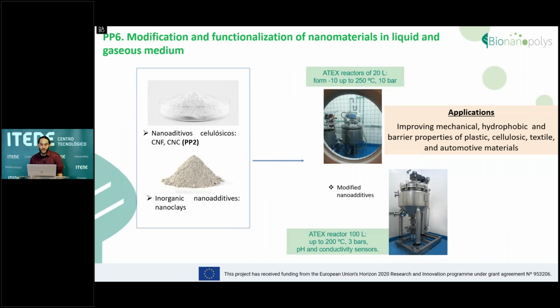Firstly, we can modify both the cellulosic nanoadditives like cellulose nanofibers and nanocrystals and inorganic clays with our ATEX reactors. As I was saying, these ATEX reactors allow us to go from 20 liters to 100 liters and temperatures up to 250 degrees Celsius and apply pressure as well. We have detectors in our ATEX reactor of 100 liters that allow us to follow the reaction using the pH sensors and the conductivity sensors. And these modified clays then are better dispersed into the biopolymers.